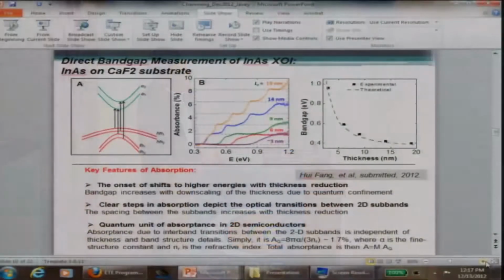And from that, you can directly measure your effective band gap, which is basically the spacing between your lowest, your first hole subband to the first electron subband. And you can see that when the film is 20 nanometer, the band gap is roughly 0.4 electron volt. Not exactly bulk yet. Bulk is 0.36. So there is some quantum confinement effect, small, but it's still there.